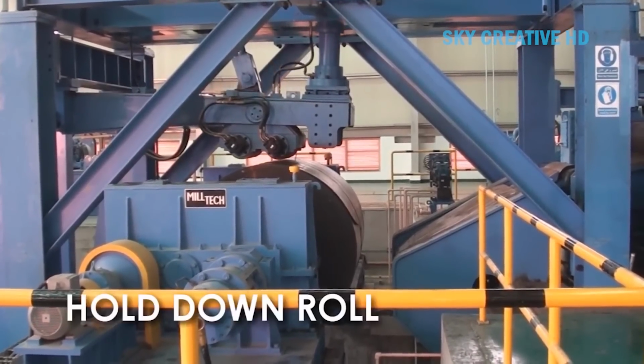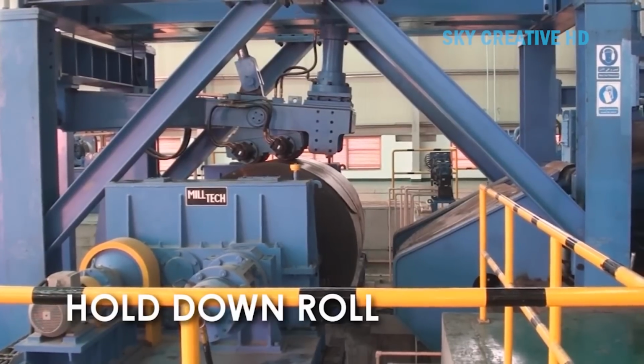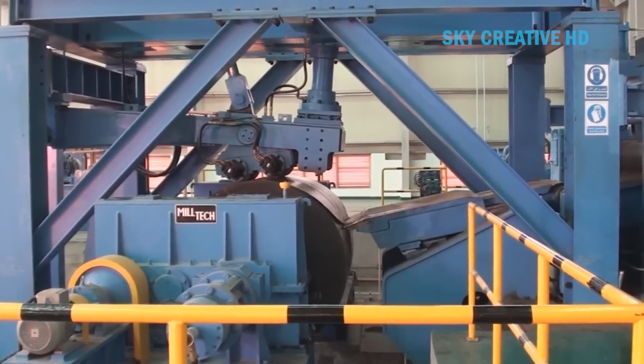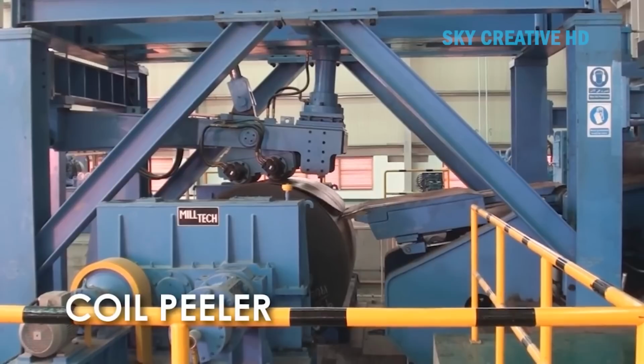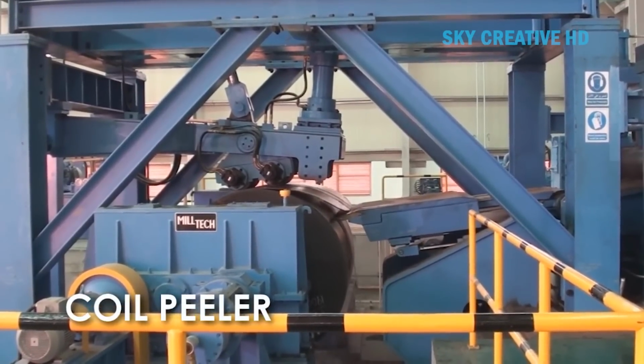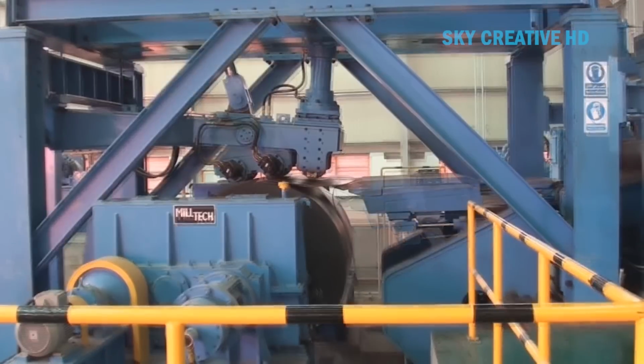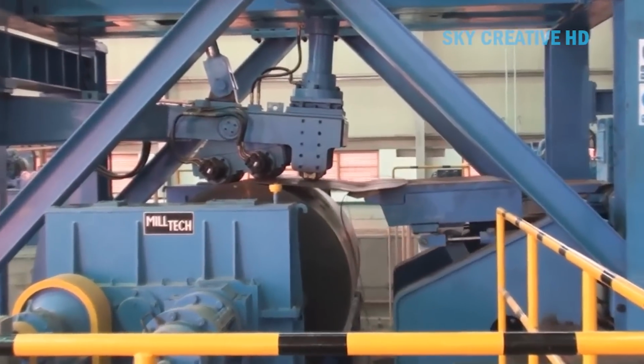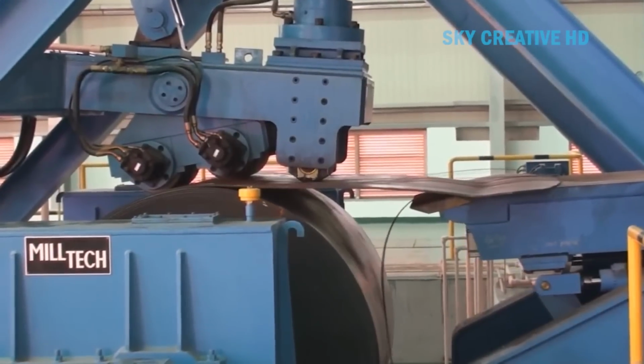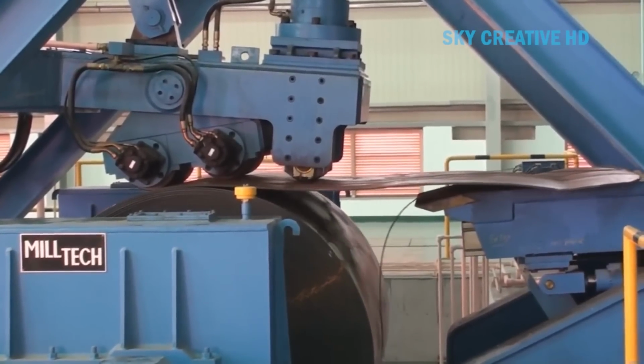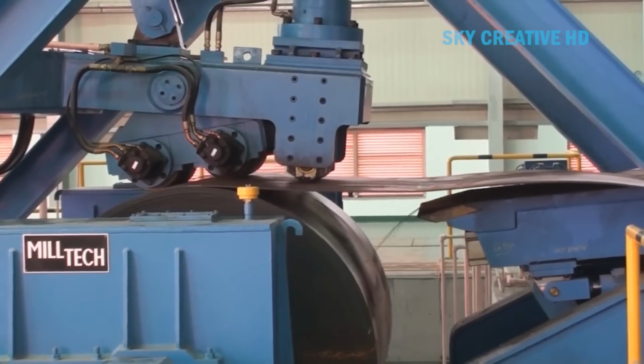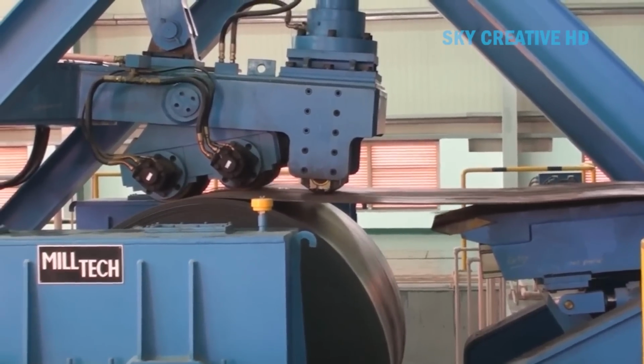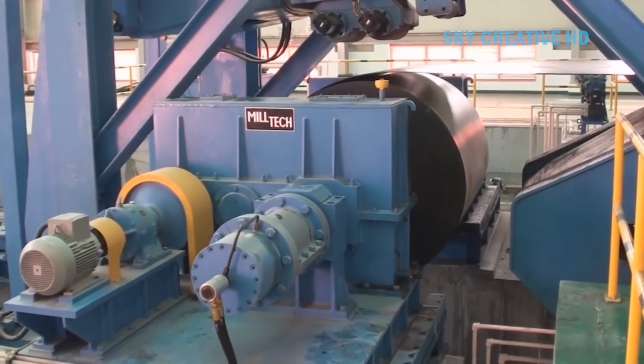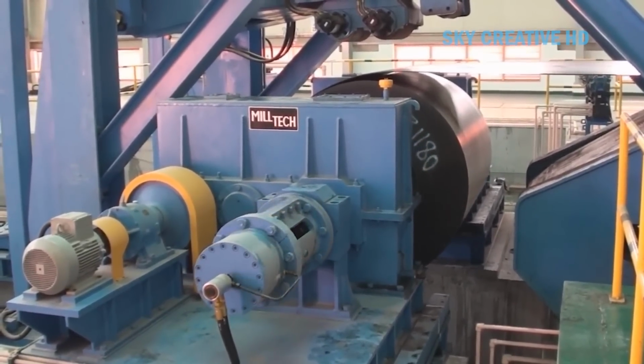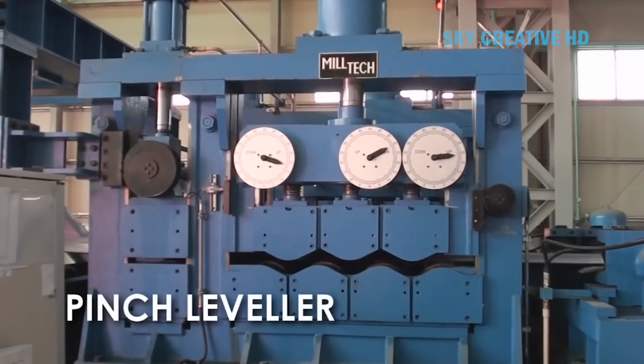The Yoder cage forming system was first installed and converted in 1969 by Bethlehem Steel Corporation on their 16-inch tube plant in Sparrows Point, Maryland, USA. It forms tubes from 5-9/16 of an inch to 16 inches in diameter. Dimensions such as 8-5/8 in by 0.125 in, 10-3/4 in by 0.156 in, and 12-3/4 in by 0.188 in that could not be formed on the original mill were successfully rolled with higher production rates.